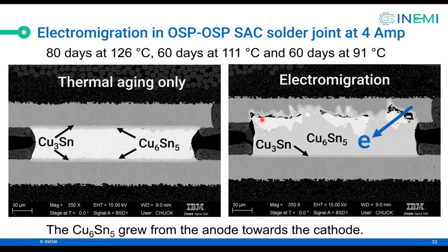And also notice the voiding. So voiding is because more atoms are flowing away from the interface than into it. So less atoms are coming in, more are leaving, and that is what is causing the voiding. So we get Cu6Sn5 consuming the solder, and of course voiding.